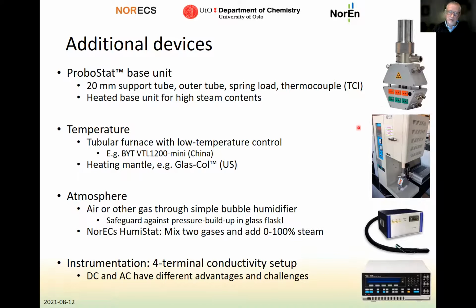You need to control temperature. For this, you can use a furnace. For instance, there is a Chinese low-cost furnace that can control temperatures very well, all the way down to room temperature. Or you can use a heating mantle from, for instance, Glascol in the US for controlling temperatures up to a few hundred degrees.